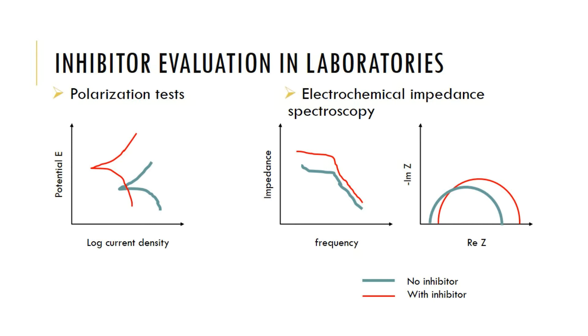In the Nyquist plot, we see two semicircles. These semicircles indicate that there is a film of inhibitor on top of the metal substrate. In the solution with inhibitor, the semicircle stands for the film of the inhibitor on top of the substrate. In the plot for a sample in a solution without inhibitor — the blue plot — the semicircle indicates that there may be a formation of a double layer next to the substrate.